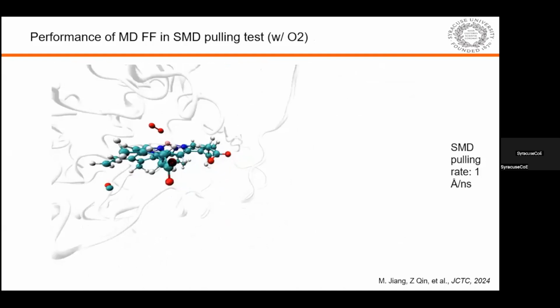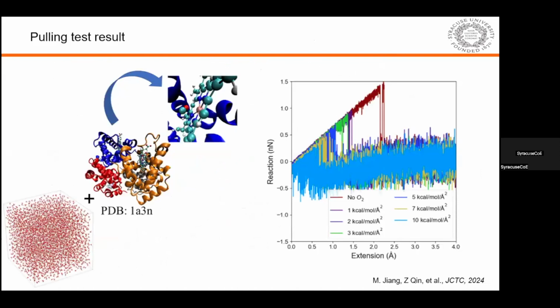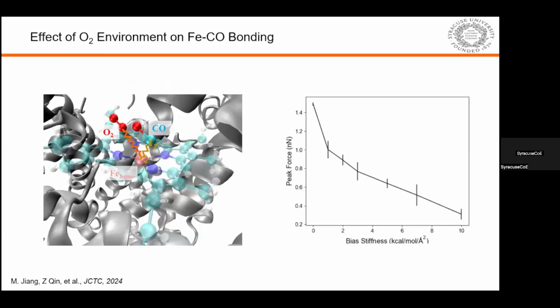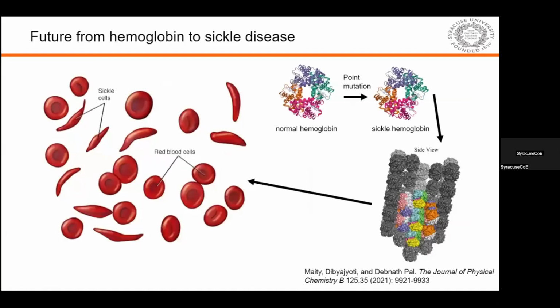We see that once we put oxygen closer and closer to this binding site, the binding between hemoglobin and the carbon monoxide becomes weaker and weaker. That's why the high pressure oxygen chamber can be effective to get rid of this toxic state. We summarize the results, showing this bias stiffness that is proportional to the constraint between hemoglobin and the oxygen. Once that increases, it means you force the oxygen closer to the binding site, and the peak force to remove the carbon monoxide becomes smaller and smaller. So we are very happy about the preliminary results based on that.